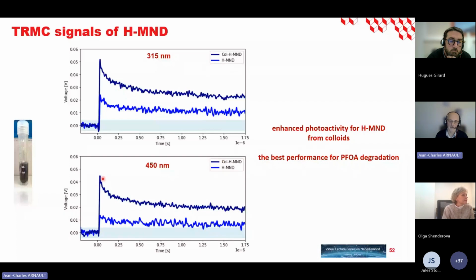You can see that for the visible range, these particles that come from the colloid also show a very interesting signal in photoactivity. So this result looks very interesting because remember that these particles give the best performance for the PFAS degradation. Of course, we have to understand more what we can learn about the TRMC signal and so on.